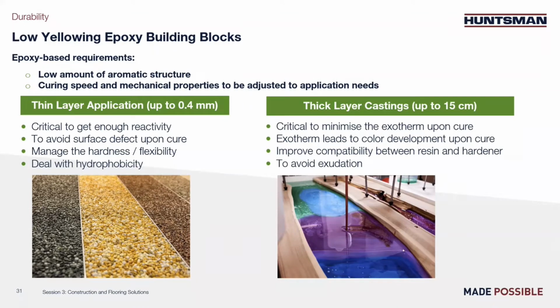We find two different applications for low yellowing. The first one would be with thin film application, and it is then critical to get a good reactivity, otherwise you would have a dreadful surface. And then there is no point in being low yellowing if it's a bad surface. A second application can be like the river table on the second picture on the right, where you have a very thick layer casting up to 15 centimeters, for instance. In that case, it's critical to limit the heat development, or also called exotherm, when the epoxy cures. Hence, you need a very low reactive system.